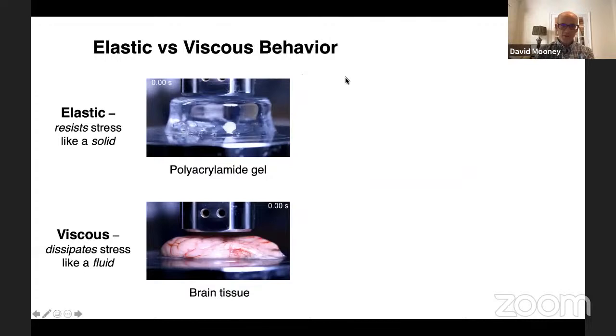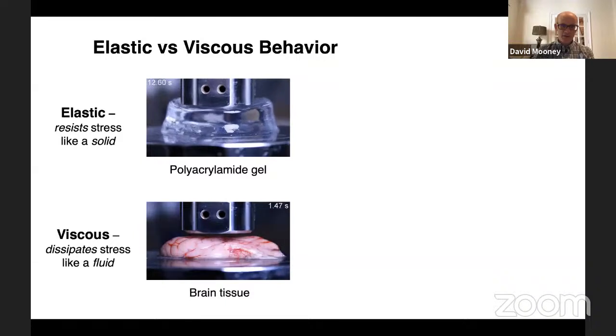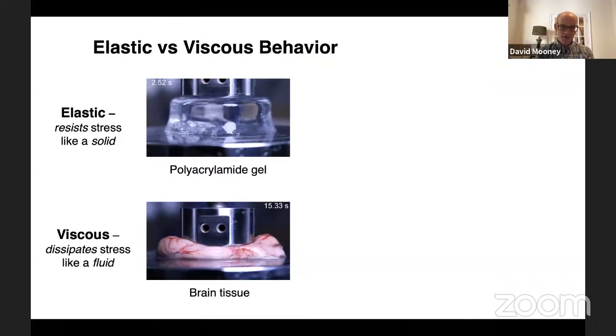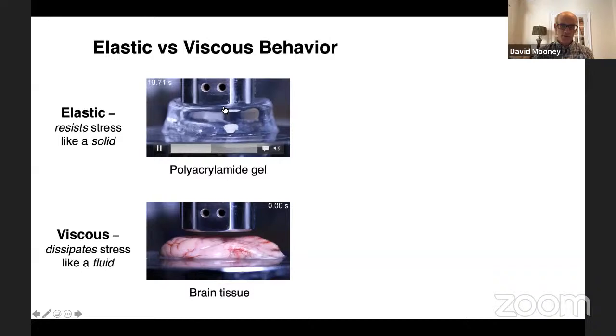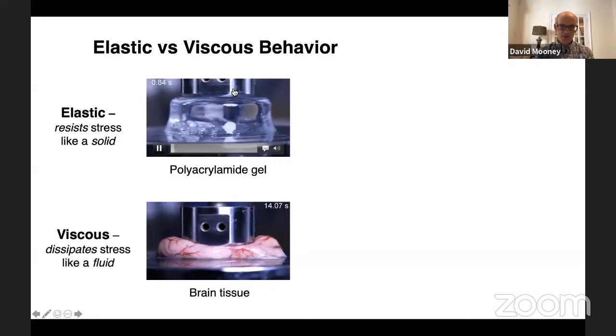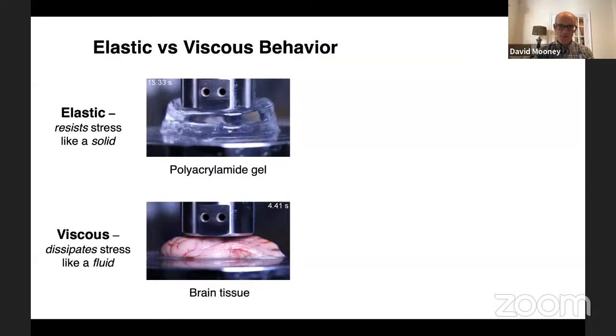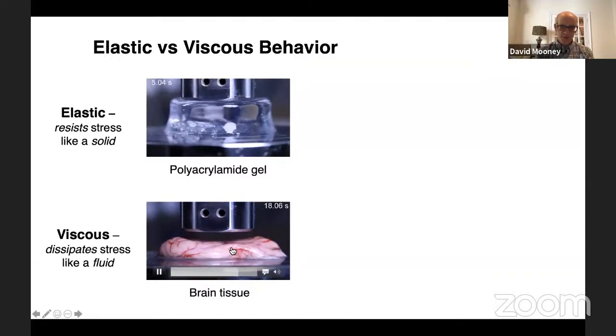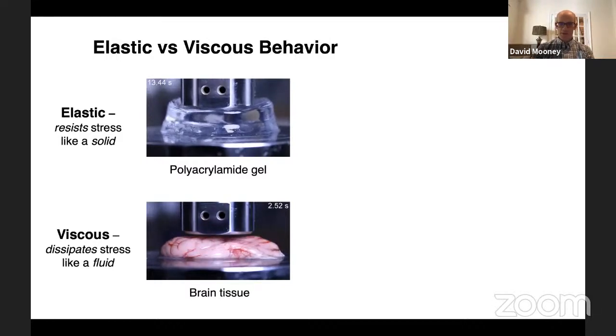Now, to give you a little bit of a visual sense of what viscoelastic and elastic materials are and how they differ, here are some videos of a purely elastic material being deformed on the top, a polyacrylamide gel, and a tissue, brain tissue in this case, being deformed on the bottom. And what you can appreciate from the material on the top is that as we basically apply a load, the material deforms, and then immediately upon release of the load, the material elastically and instantaneously goes back to its original dimensions. In contrast, in the viscoelastic material on the bottom, you'll appreciate that after we remove the load, some significant deformation remains in the material. So it's actually exhibited some flow. It's dissipated some of the energy that we put into it.